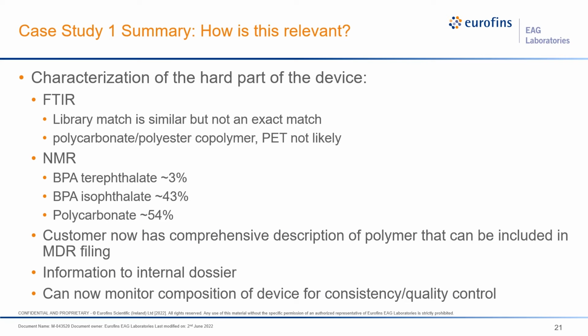So what do we learn from this first case study? Analyzing the hard part of this medical device was able to let us know what the exact composition was. So we got a good idea what it was from FTIR, that it was some sort of a polycarbonate polyester mixture, and that PET may not be exactly what we're looking at. Using spectra and literature databases, we were able to determine using NMR spectroscopy that it's actually a bisphenol terephthalate isophthalate polycarbonate mixture. So now this customer could take this data and file it in their MDR and be confident that they know everything they need to know about this polymer's composition. They can add this information to their internal dossier, and they can also monitor this composition over time for quality control and consistency.